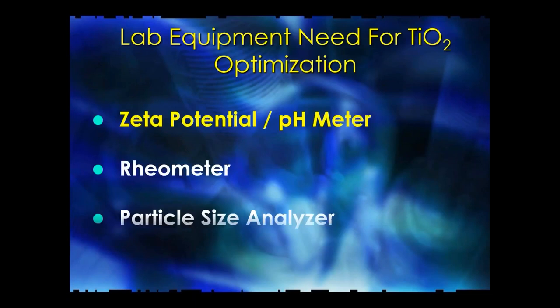Okay, in order to be able to determine whether or not you have a pigment which will give you high hiding power, you need, very basically, 3 things. You need to know what the charge is on the titanium dioxide, because opposite charges attract, and you need enough charge to keep the pigment dispersed. But the charge varies as a function of pH, so you need a pH meter. And you use a rheometer to determine whether you have the dispersant properly applied. In other words, how liquid is it? And you also need a particle size analyzer.